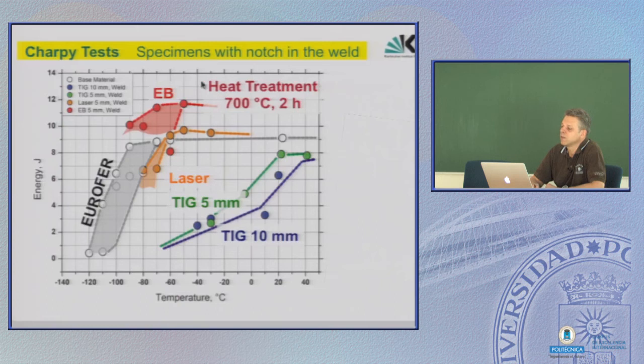So a heat treatment of only 700 C for 2 hours results in such a picture. And this is quite promising. The EB welded parts are perfectly in line with the base material. Also, the laser weld is at least near the results of the base materials. And don't be astonished that some of the welds show even higher energies in the fracture compared to the base material. That's only a geometrical thing.